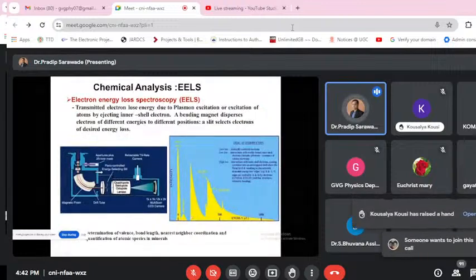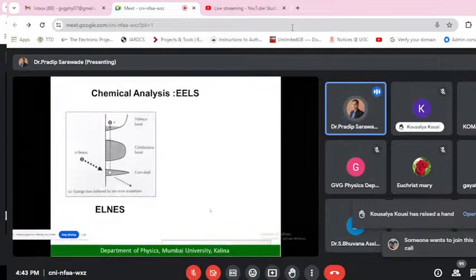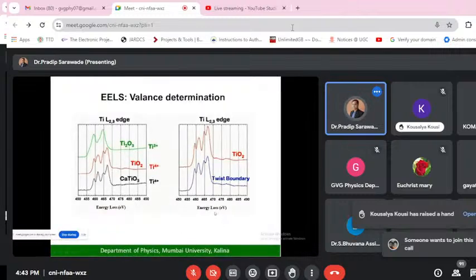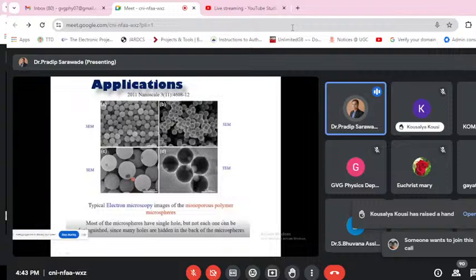When I was in Saudi Arabia, at KAUST, I used this. Normally, a fully equipped TEM is used with EELS, and it costs around 55 crores. It is very expensive because it has EDX and EELS, because you can find out how much energy loss there is from your sample, and from that energy loss you can find out the defects of your sample. Due to time, I skip this EELS technique. You just observe the energy loss using the detector after passing through your sample, and you get different kinds of defect patterns. Oxidation state you can also find out using EELS. So this is an advanced technique actually.